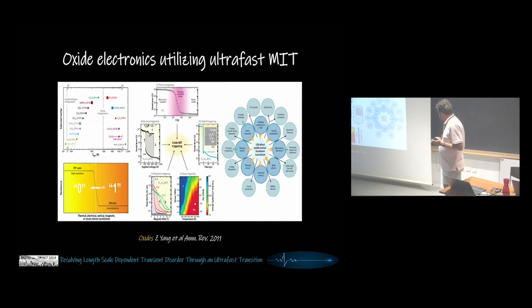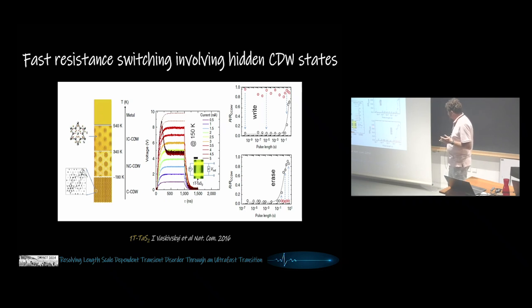So here is an example of that. This is ultrafast resistive switching in the famous 1T tantalum disulfide. This is work done by the group from Ljubljana. You can apply a pulse, you can write, so change the resistivity. You can apply another pulse and you can erase the state. So that's the idea.